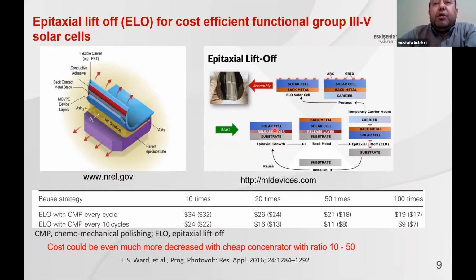When you look here, you first grow your devices, for example, solar cells in inverted shape, which means the top junction is grown first, the last junction grown last. Then you deposit the metal back contact of the low energy junction. Then by using the ELO technique, you just lift off these solar cells to the carrier. Then conventional device fabrication goes on.